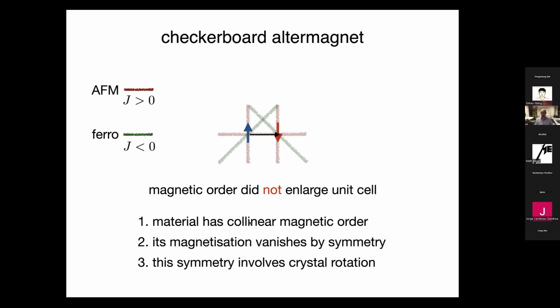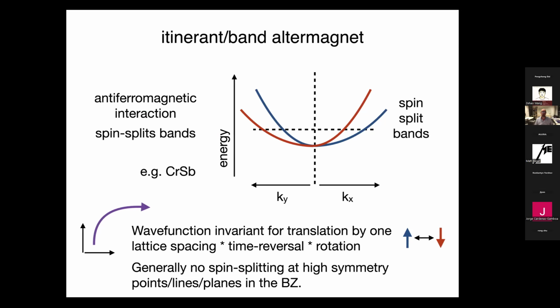This material has collinear magnetic order. This model has collinear magnetic order. Its magnetization vanishes by symmetry, and this symmetry involves crystal rotation. Now, if I look at a band structure of such an altermagnet in an itinerant picture, then I'll see that at a generic momentum, there is a spin splitting of the bands. And if I do a rotation, for instance, I rotate kx to ky, I get again the same band splitting, only the up and the down bands are changed. So this reflects that at a generic momentum, rotation does not leave the momentum invariant.